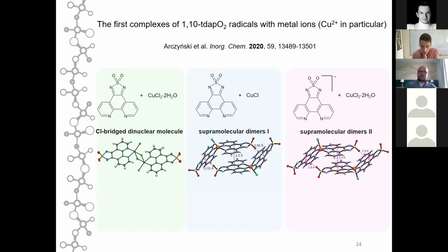So after that, since Kunio Awaga didn't report any coordination compounds with radical 1,10-phenanthroline dioxothiadiazole radical anions, we focused on this aspect of these radical anions, and we managed to obtain a series of compounds with copper. And you may wonder why we chose copper. Copper is quite simple. It's a spin 1/2 system, and so it's easier to analyze what's happening in these kinds of compounds with copper rather than in cobalt or nickel molecules.